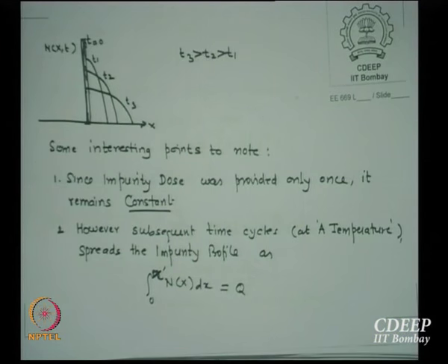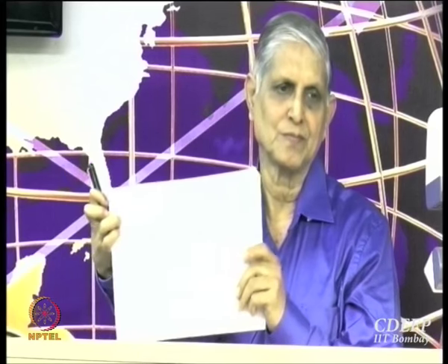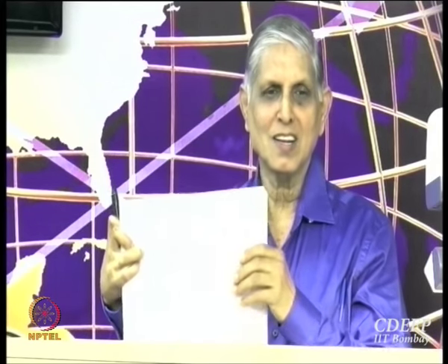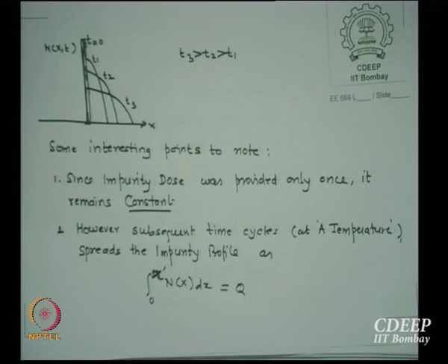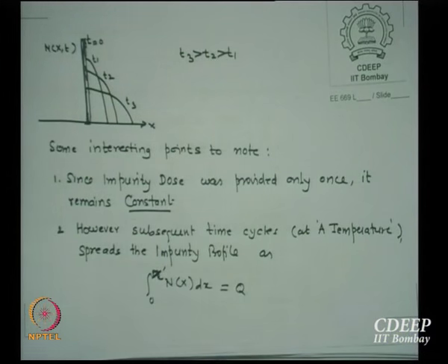Now one question which I have not said very clearly here: if you have a silicon surface, maybe a paper itself, and there is a sheet charge sitting here, silicon here, but on this side there is air. If I heat it, the impurities have no choice of direction. They may get inside silicon, but partly may go out. This is called out-diffusion. Then the next time, the impurity amount would not be Q, because part of the impurities are already lost in the air. However, that never happens in a real device. The reason is that during the drive-in, this time-temperature cycle, we actually do this process, and we shall see the technique a little later, in oxygen ambient.